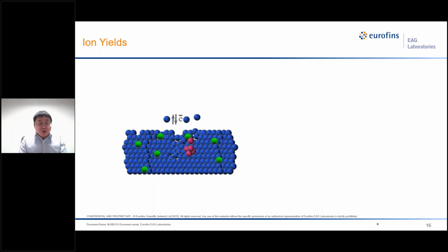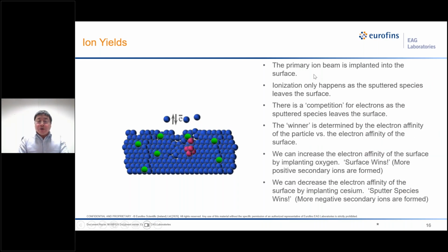So as I mentioned in previous slides, most of the species are neutral. So how to improve the ion yield? The primary ion beam is implanted into the surface. Ionization only happens as the sputtered species leave the surface. There's a competition for electrons as the sputtered species leave the surface. The winner is determined by the electron affinity of the particle versus the electron affinity of the surface. So we can increase the electron affinity of the surface by implanting oxygen, because the oxygen will draw electrons, so there are no electrons available to neutralize the positive ions. In this case, more positive secondary ions are formed.